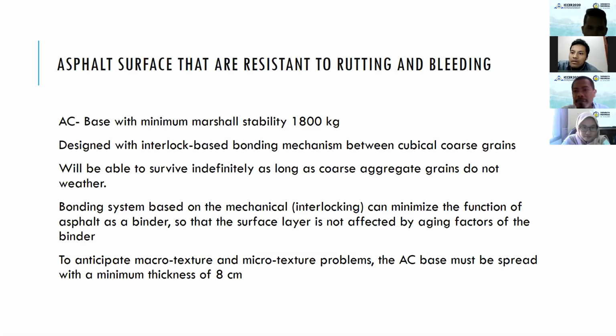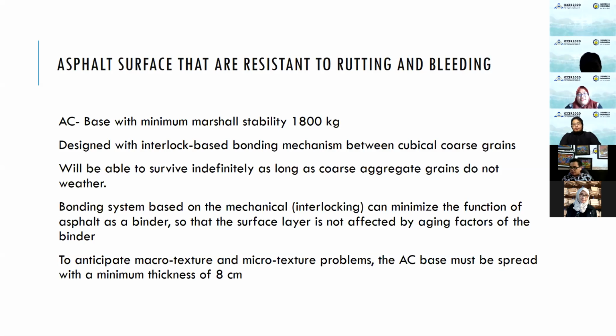Bonding system based on the mechanical or interlocking can minimize the function of the asphalt as a binder, so that the surface layer is not affected by aging factor of the binder. To anticipate macro texture and micro texture problem, the asphalt concrete base must be spread with a minimum thickness of 8 centimeter.